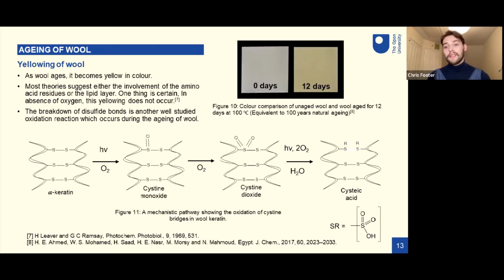These are two of my own samples. They're both wool, Nuns veiling, which is a plain weave. And as you can see on the left, we have an unaged sample of wool. And on the right, we have a sample that's been aged for 12 days at 100 degrees Celsius. These specific values were chosen because Ahmed et al. had suggested it being equivalent to 100 years of natural aging. One thing I do want to do in my research is see the validity of this statement.